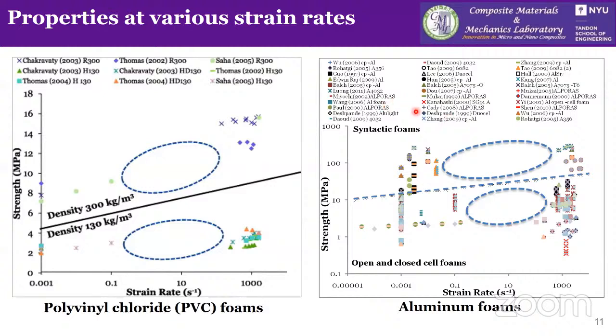Some of this may be, but mostly it's taken from other studies. Then what you see here is that despite having all these different types of methods, there are still large ranges of strain rates where there is no data available in the published literature. So usually for PVC foam, from about 1 to about 500 per second strain rates, there's no data reported in any of the studies. For aluminum foams, same range, about 0.1 to about 500 per second. There's no data reported in any of the studies.